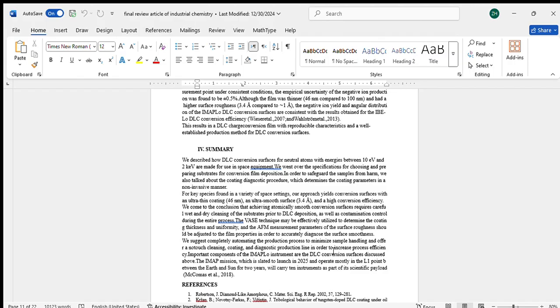Use of VASE and AFM. Variable angle spectroscopic ellipsometry was used to measure the thickness and uniformity of the DLC coating, while AFM, atomic force microscopy, was used to measure the surface roughness. These tools were crucial for monitoring the quality of the conversion surfaces during production. Automated production process: to further improve the efficiency of the production process, the authors recommended fully automating the process. This would minimize handling of the sample, reduce contamination risk, and improve overall production efficiency.